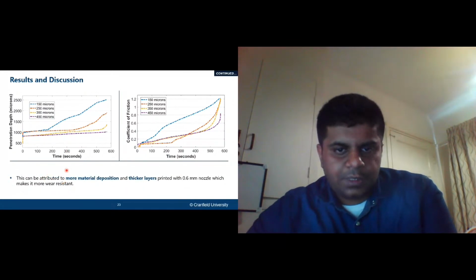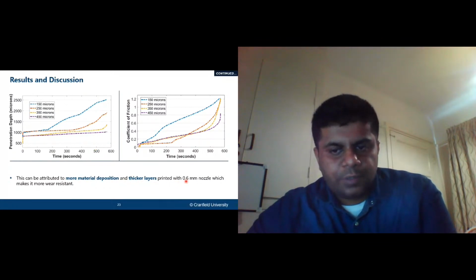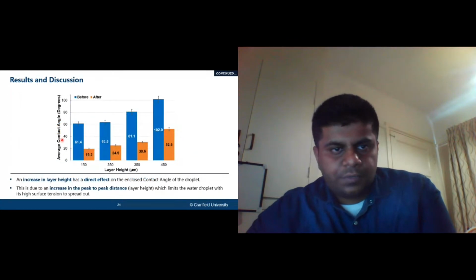And this particular change can also be attributed to more material deposition and thicker layer when printed with 0.6 mm nozzle, because obviously when you change the height and you change the diameter of the nozzle itself, you end up with more material being deposited per layer, which can also be attributed to this trend. But the more interesting effect was this one, because as you change the layer height, you end up with higher contact angles as well, as can be seen over here. So for each layer height, you're getting a better contact angle. This is due to an increase in the peak-to-peak distance, which is layer height, which limits the water droplet with its high surface tension from spreading out.